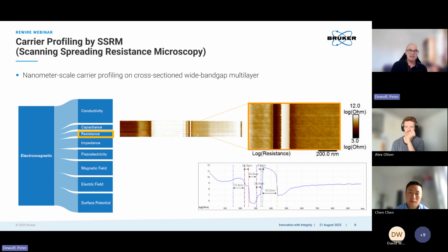But the resistance map shows the multi-layer structure of that sample. The colors here represent the log of resistance between the tip and the sample, and that resistance directly scales with the carrier concentration, or reverse scales with the carrier concentration of the sample.